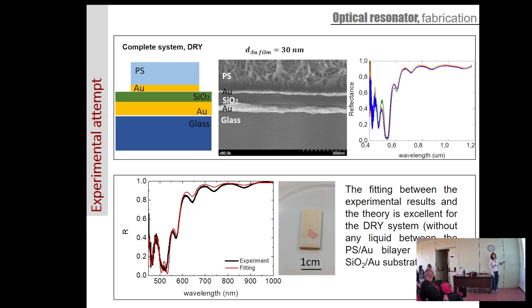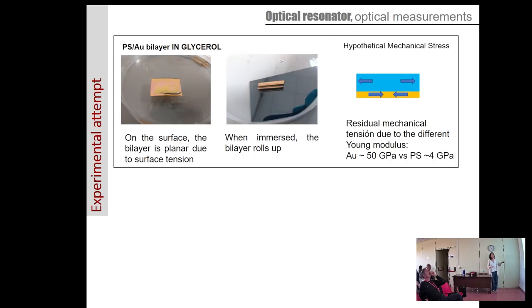This is how it looks, the polystyrene, gold, silica, gold glass. We characterized it spectroscopically. We did the fitting, everything was fine. But then we included glycerol and our sample started to roll out, and we had to deal with this for a long time. We believe that we had some mechanical stress between the polystyrene and the gold.